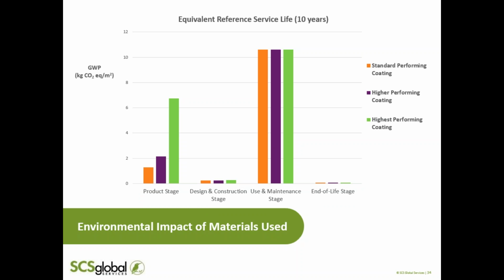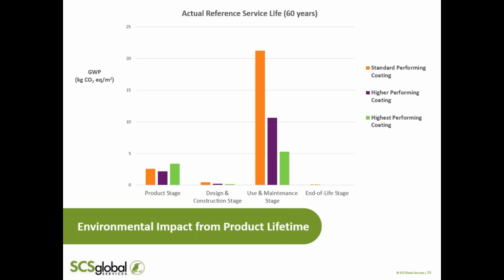We can see that the highest performing coating, shown in green, has the largest global warming potential compared to the other powder coatings. However, if we change the reference service life to a 60-year period instead of 10, which is the expected lifetime of a building, the results essentially flip. This is due to the fact that the standard and higher performing coatings have a relatively lower expected product lifetime than the highest performing coating and need to be replaced more often. This is despite the highest performing coating having the largest upstream impact relative to its lower performing competitors. As such, in some cases, a higher quality and better performing product may have a larger upstream impact relative to its lower performing competitor, but ultimately have a lower total impact after accounting for the expected product lifetime.